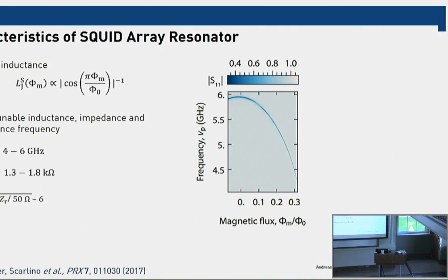And this you can then verify easily. You do a microwave reflection spectroscopy experiment. So this here is the S11 parameter, the scattering matrix measured of this device in reflection. At zero applied magnetic field, you see a maximum frequency resonance at around 6 gigahertz, and then you apply magnetic field, and the resonance frequency comes down.